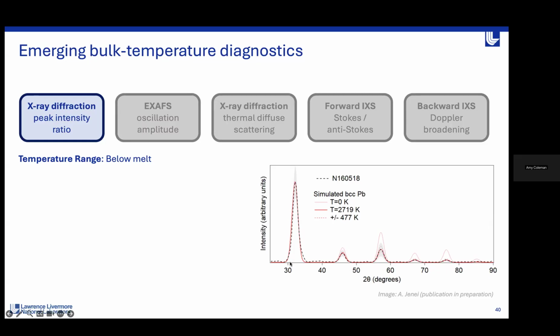This is preliminary work really being led by Amy Jenei here at the lab. She has a really nice data set on lead, where she's currently using this technique to extract a temperature. Comments on this technique: it's only really valid if you're in the solid regime, you need these intense peaks in order to infer a temperature, and you can't really do this on a diffuse liquid scattering signal. It also relies on a Debye model. But it is a good technique that is being developed.